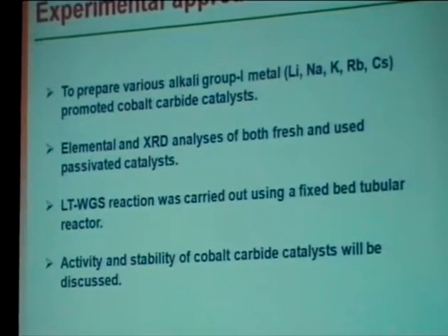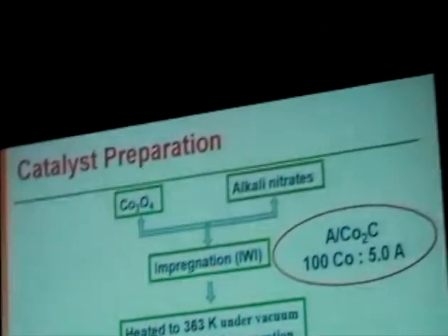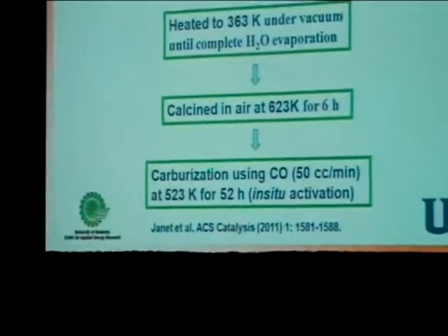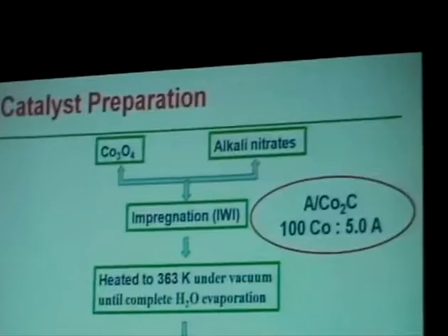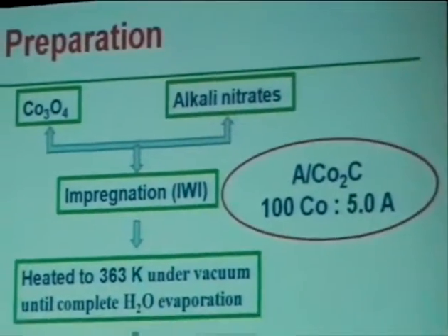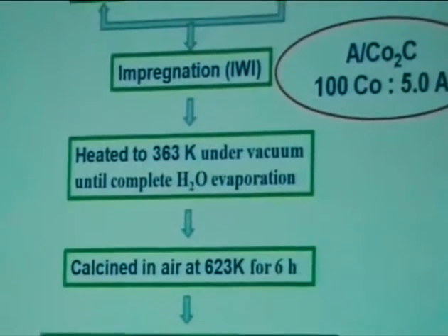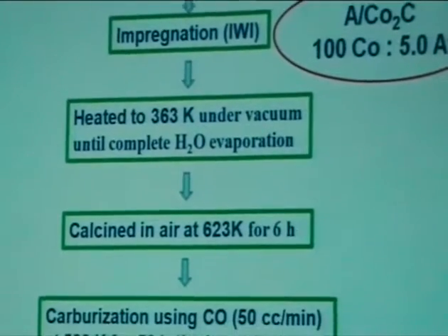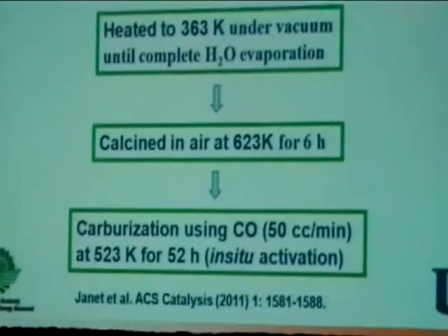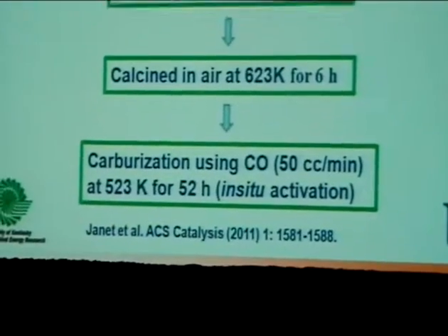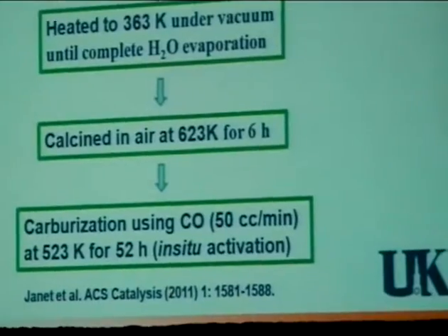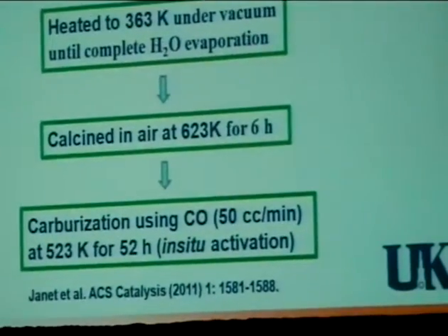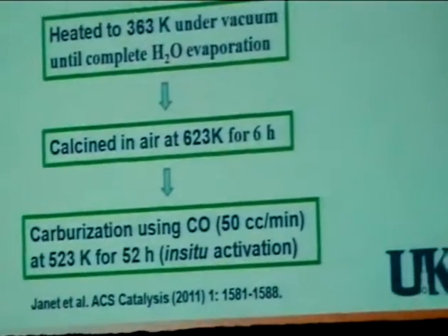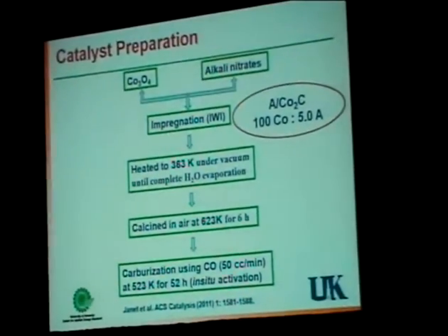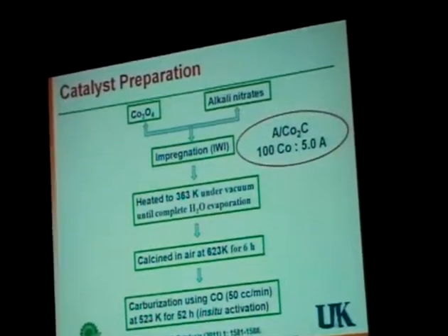and finally compared the activity and stability of the catalyst. So we prepared this catalyst by impregnating the alkali nitrates by incipient wetness impregnation, with atomic ratios in the range of 100 cobalt to 5 alkali metals. And after impregnation, we just dried it, and then the usual calcination for 6 hours. Before doing the run, we did a carburization in situ using CO at 523 K for 52 hours.